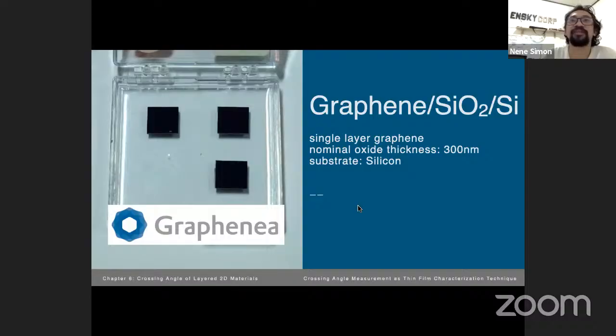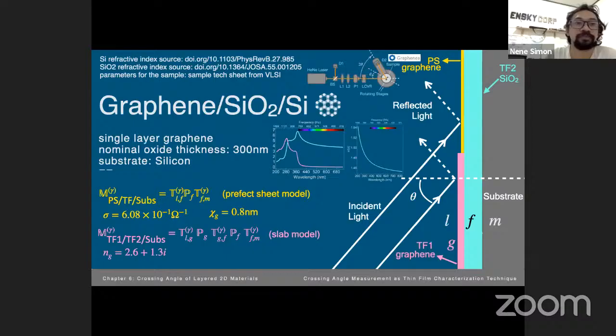So our sample is from Graphenea, and this sample has a single layer graphene on its topmost, then followed by a silicon dioxide layer whose nominal thickness is 300 nanometers on a silicon substrate. So the total thickness of this sample is 525 plus or minus 20 microns. In their theoretical calculations, the single layer graphene here has a thickness of 0.345 nanometers. So the refractive indices for the silicon dioxide and silicon material are assumed to follow the values in the literature.